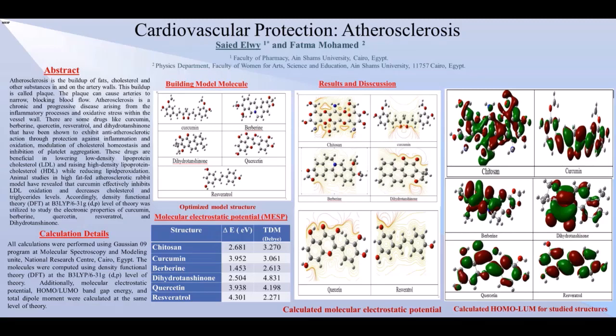levels. Accordingly, density functional theory (DFT) at B3LYP 6-31G d,p level of theory was utilized to study the electronic properties of curcumin, berberine, quercetin, resveratrol, and dihydrotanshinone. Calculation details: all calculations were performed using Gaussian 09 program at Molecular Spectroscopy and Modeling Unit, National Research Center, Cairo, Egypt. The molecules were computed using density functional theory at the B3LYP 6-31G d,p level of theory. Additionally, molecular electrostatic potential, HOMO-LUMO band gap energy, and total dipole moment were calculated at the same level of theory.